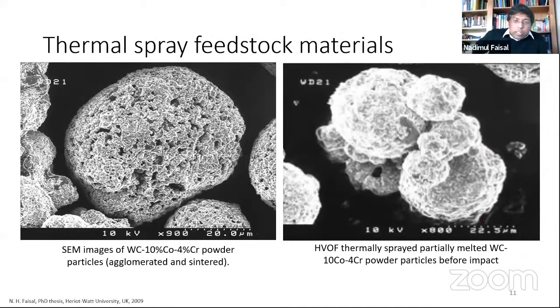Right, these are examples of powder particles. On the left side is before you spray, and on the right side is when it is going through the spray and before it lands. We collected some powder particles. You can see the surface is partially molten and a few particles are joined up, and that will eventually land on the substrate and form a splat. Either it is a proper splat or it can disintegrate into smaller particles. So in the first layer, it will interact with the rough surface, and that is where the mechanical interlocking would happen.